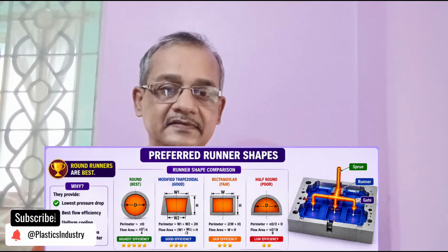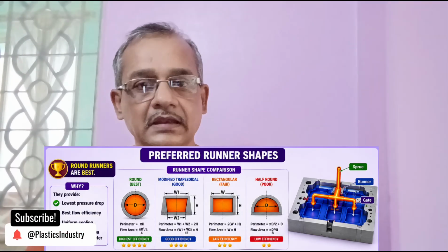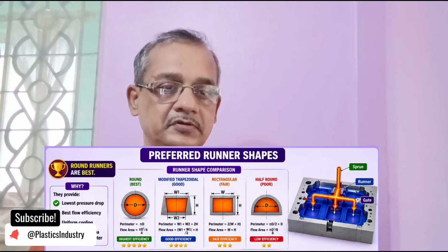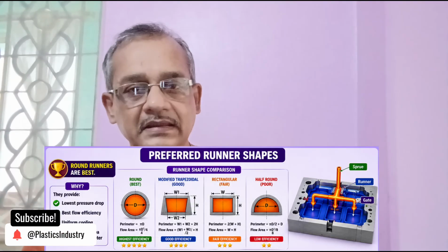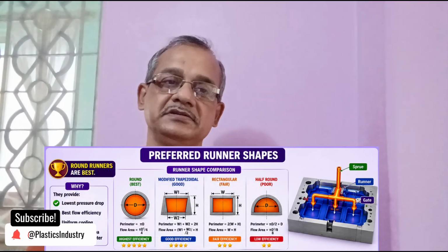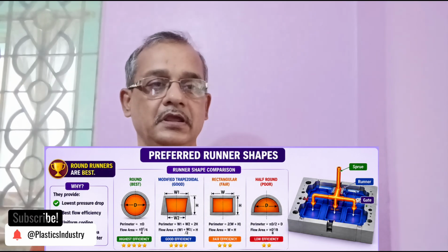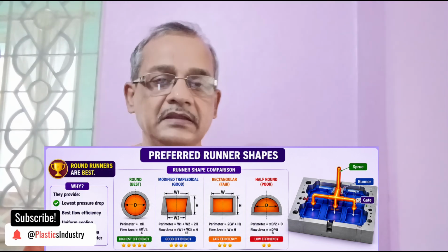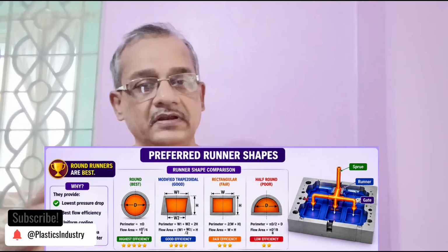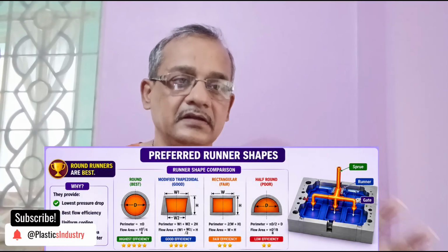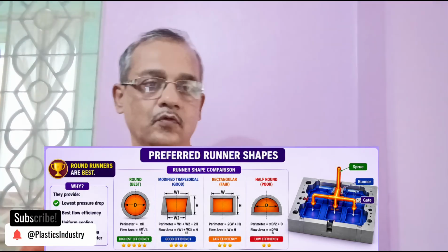Now, balancing material flow in multi-cavity molds. This is where many designers struggle. Imagine a 4-cavity mold. If runner lengths are unequal, some cavities fill first, others fill later. What is the result? Weight variation, dimensional variation, flash in some cavities, shorts in others, poor process stability, customer complaints.